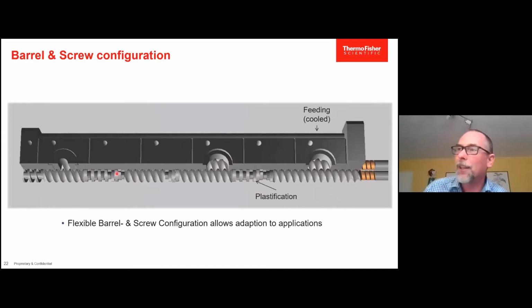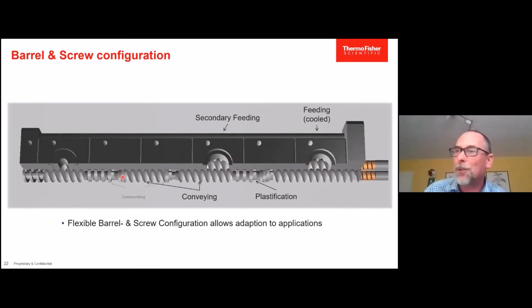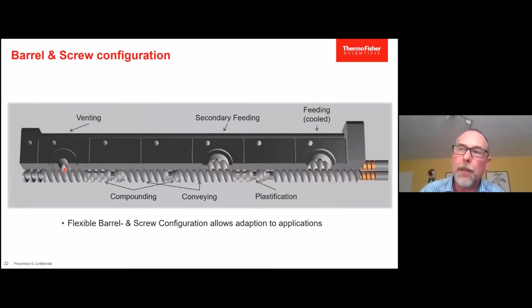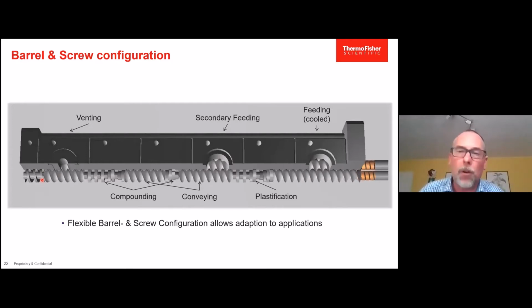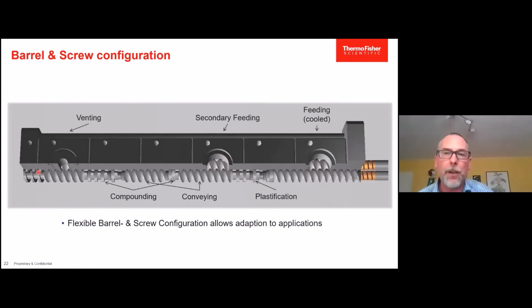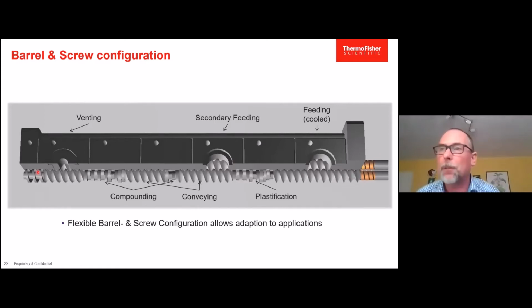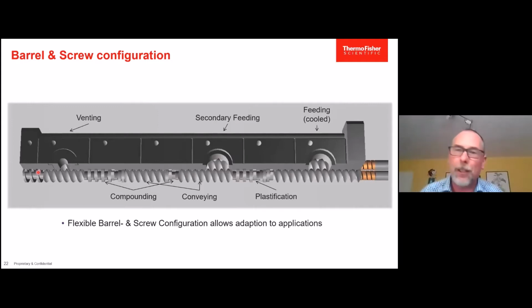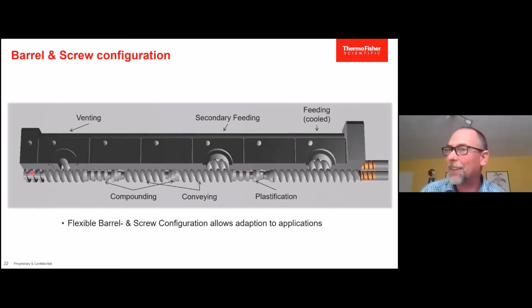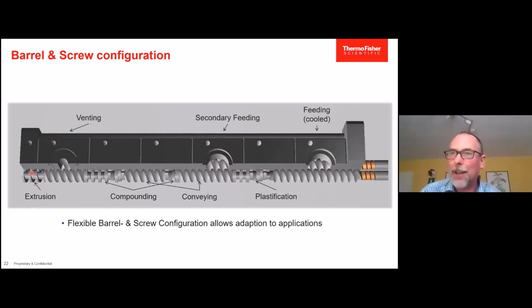And what I forgot is to show you the different steps, which I will do now. So you see up to 3 compounding zones, 1 zone for venting, and here are always special elements which have less volume to compact the material, to increase pressure, so that we can go over to the next step of the process, which usually will be a strand production, a sheet production, a blown film production, or convey it to another instrument like a small injection machine, or to convey it to a melt pump, for example, right? So we call this the extrusion elements.